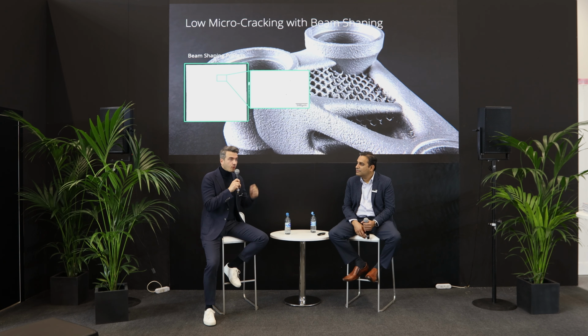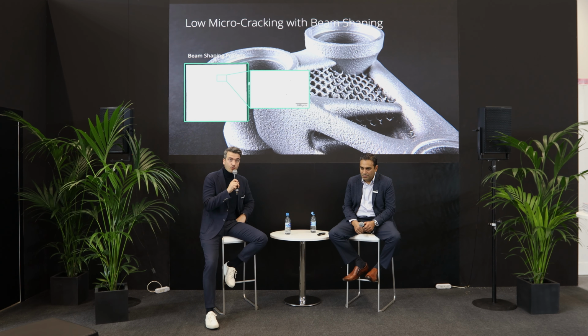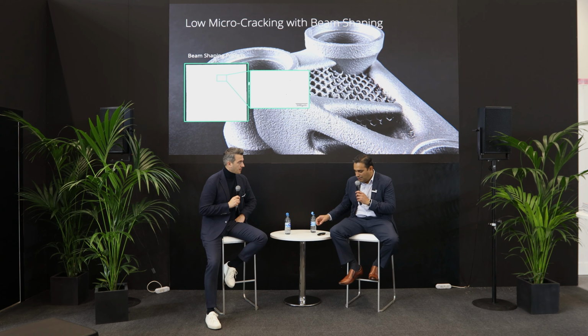Not only in the infill on the Inconel 718, we also did other materials already, like aluminum, AlSi10Mg, but also MAR247. We tested it already, and there we really see that we are having super low porosity. We're at 99.99% over there, and also the pore size itself. We want to go below 40 microns, right? This is the target, pores below 40 microns, which we get from our customers as requirements, and with this new approach, even with such high productivity, we meet it, and this is the magic behind. No, absolutely right.